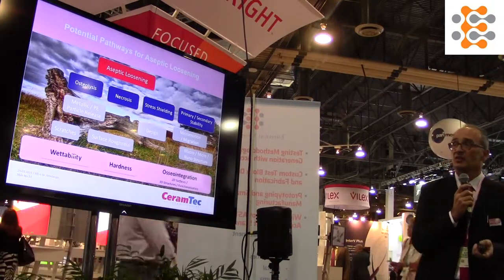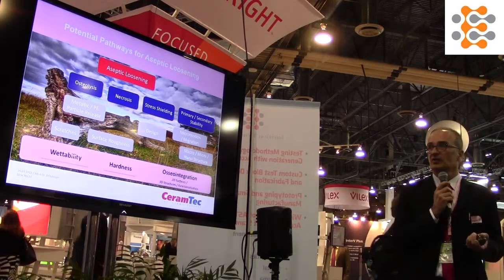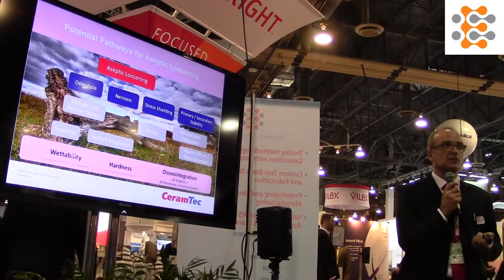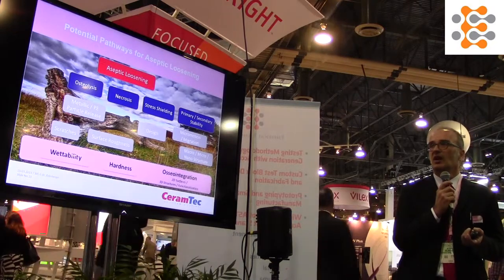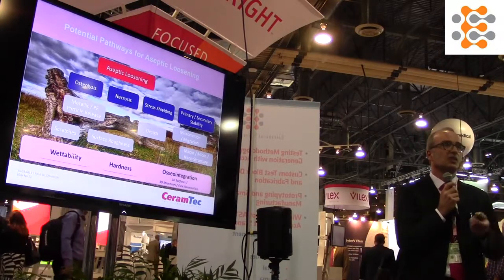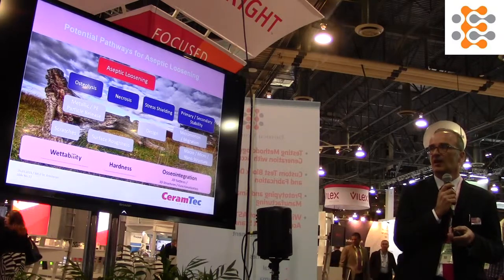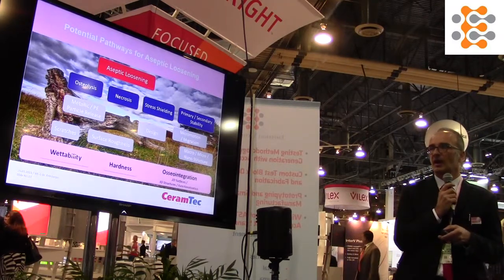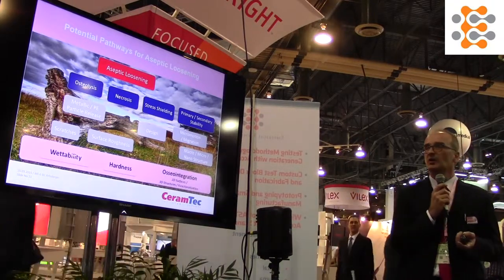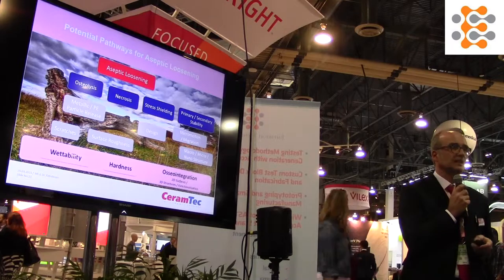If you look at, for instance, aseptic loosening, what leads to aseptic loosening? This is, for instance, osteolysis. What causes osteolysis? It can be particle release, for instance, polyethylene particle release. What promotes particle release? This can be scratches, surface roughness. So what can you do on the material side? You can address those issues by controlling the material, for instance, in terms of hardness. When you have a hard material, you can have a high surface quality, you can have fewer scratches, and then you can help to reduce those clinical challenges.